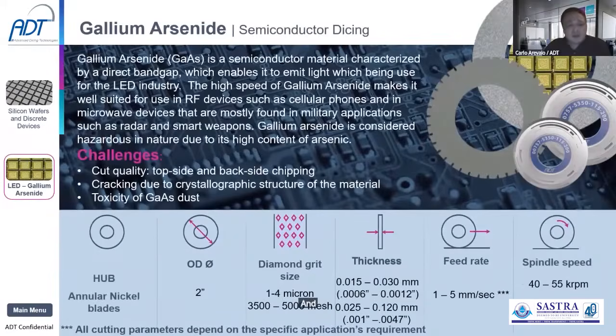And gallium arsenide is a semiconductor material characterized by a direct band gap, which enables it to emit light. So for the LED industry, for LED packaging, sawing gallium arsenide, they're always developing gallium arsenide wafers. The challenges for this kind of wafer are the same: it's the topside and backside chipping. Also, the cracking that you can develop because of the structure of how the wafers are made.